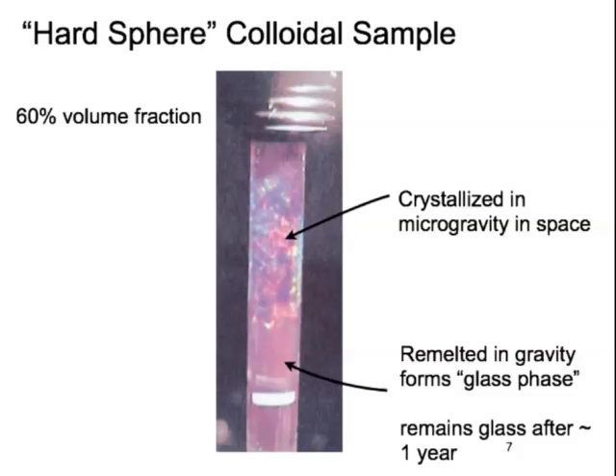It turns out the main part of van der Waals comes in the visible, so what you end up doing is index matching your sample, index matching your fluids. You take two fluids, you mix them to get the same index as the spheres, okay? So you've used two fluids. If now, in addition, you want to density match them, you have to have a third component that you add in, so you can both index match and density match with three of them, and then you vary temperature to finally do it.